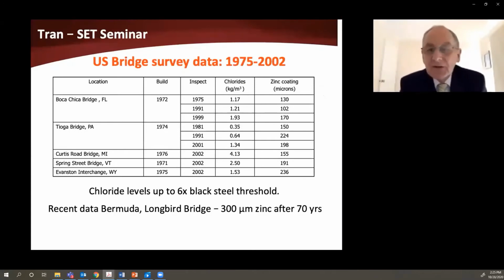Now, here's just some other data. This is a bridge survey that was done across a number of US bridges. You can see there bridges built in the 70s, basically, and inspected at various periods of time. Here are the chloride levels. And remember, there is a 0.4 kilograms per cubic meter for black steel. And here's the coating thickness of zinc left on the surface, measured. What this shows is that in this data alone, which covers about a 40 to 50-year period when these inspections were done, chloride levels were up to 5 or 6 times that of black steel.